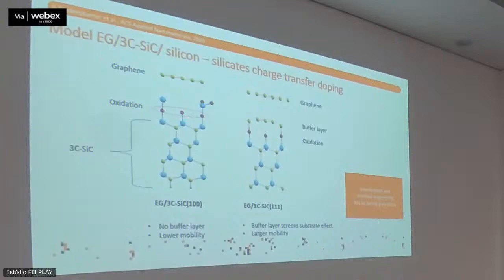most of the doping in graphene is always by charge transfer. It's not because you actually have dopants in the graphene, but it's because graphene is surrounded by certain types of materials. And that was the case also for the actual graphene on silicon carbide, it was given that type of doping. In this case, because we have an oxidation, so oxygen appearing just in front of the graphene, this would induce a p-type doping. And most importantly, you can see also this is a 100, and this is a 111, so they have slightly different configurations here.